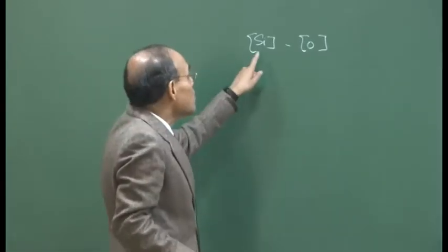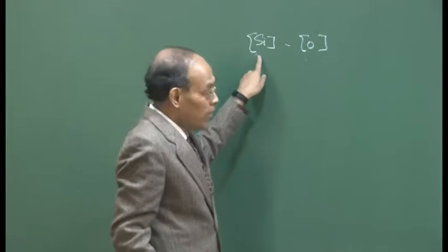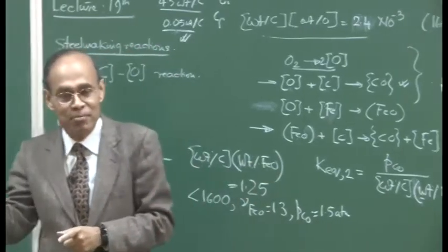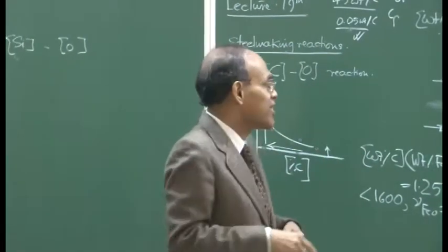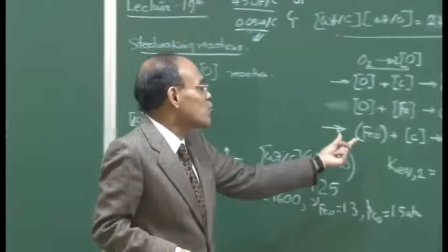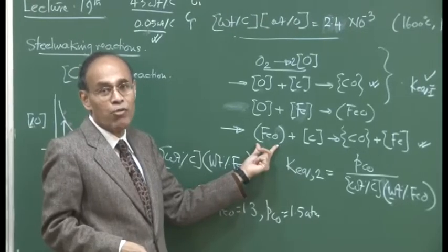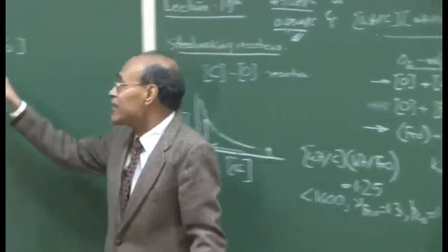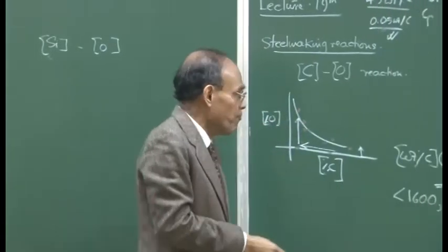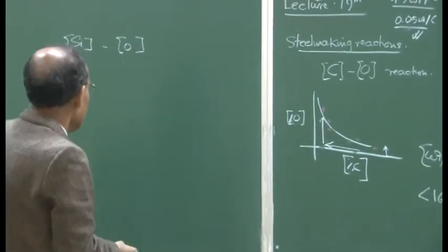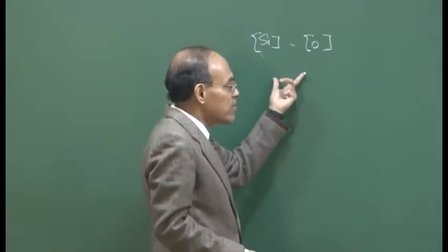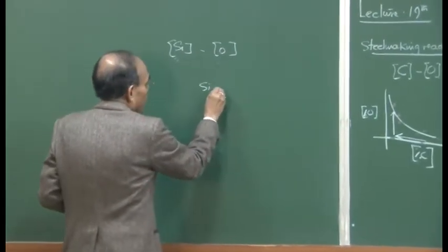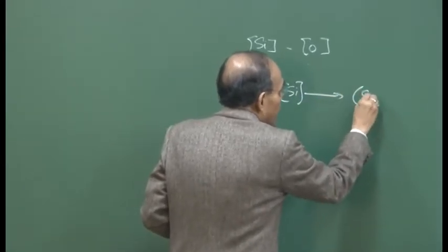Again, I repeat that it does not mean that this is the only way of reaction. Silicon can react with FeO if FeO forms and comes in contact with silicon, because silicon, according to the Ellingham diagram, has more affinity towards oxygen at 1600 degrees centigrade. If FeO forms because of its large-scale presence in the system, since 95 atoms out of 100 are oxygen or Fe, then silicon plus FeO is also a possible reaction. So we can visualize the silicon removal reaction, but no matter what happens, dissolved silicon is going to be removed as dissolved silica under steelmaking conditions.